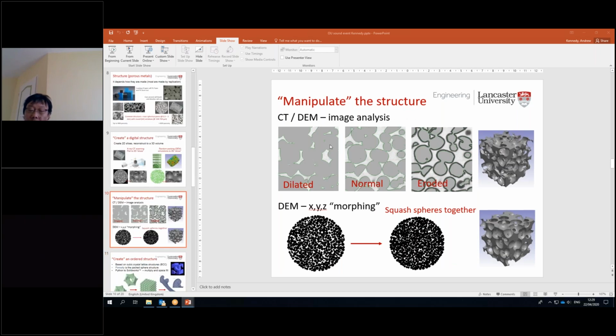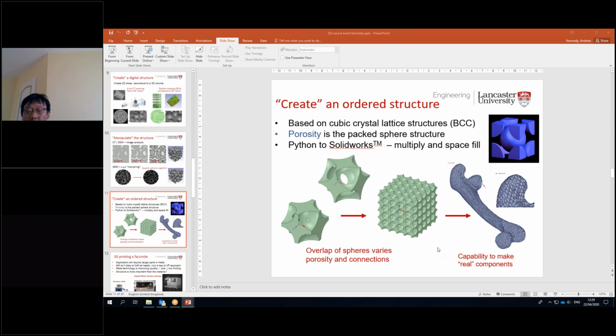We can manipulate these structures as well. For the case of CT and DEM, we can just do simple image analysis of our as-achieved structure, and we can dilate it and erode it and then reconstruct it. With our DEM models, having X, Y, Z coordinates for all the spheres, we can apply all sorts of algorithms to shear or morph or squash particles together to alter our structures. We're currently looking at those that reflect random structures. We can also look at ordered structures, and that's where we're diverting some of our attention at the moment.